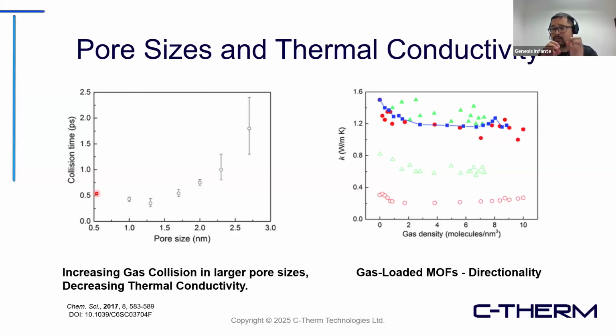If you look at it the opposite way, if you have a small pore size within that MOF, you'll still have gases within it, but the collision rate in there is going to be a lot less compared to a larger volume, so you don't see a significant effect on the thermal conductivity. Another one that the paper really covers is the directionality relative to the direction of the gas channel. There's one that's parallel to it, and then there's perpendicular to that direction. When having more gas going through, you can see that a lot more thermal conductivity is measured, while in the perpendicular direction you see a lot less. Right.